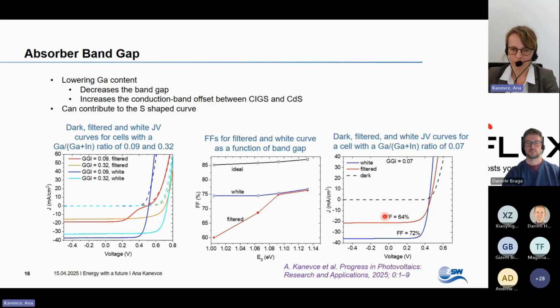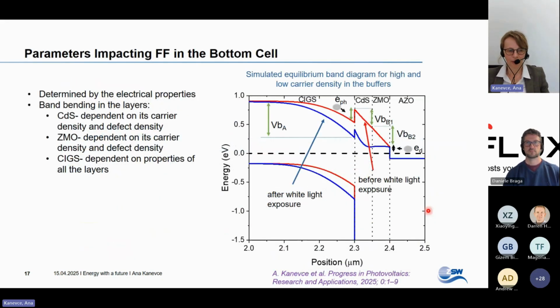Now, in addition to band alignment, there are additional suspects for such a behavior. And they come from the carrier density in the buffer layer. Now, if you look at those band diagrams, the band alignment is the same. The band offsets here and here are the same. But for the band diagram, which is shown with red, the buffer layers, so cadmium sulfide and zinc magnesium oxide, are not highly doped. Because of their low doping, there is a significant band bending in the buffer materials. What this does is this affects also the band bending in the CIGS layer.